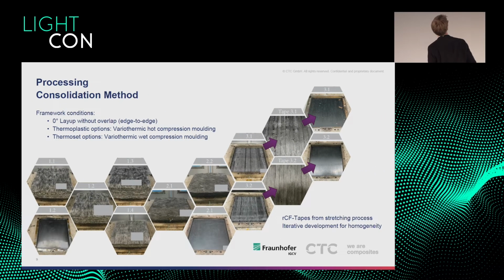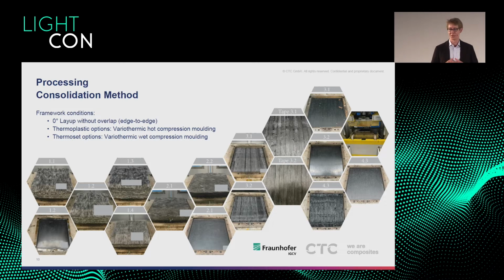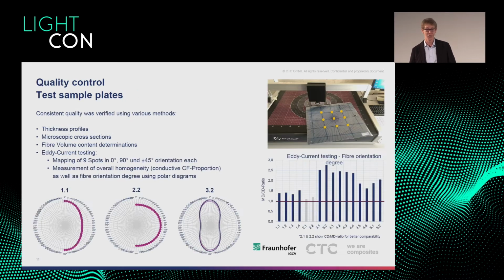For those of you who've seen raw materials or raw processing of AFP tows and any UD textile in aviation, the later images, like tape 3.2 and 3.1, actually look pretty much like an AFP tape that we're used to. We then processed those into composite coupons and did a lot of assessment. And the most important was, do we actually have a good alignment? Or is it a non-woven with a very slight preferred orientation?